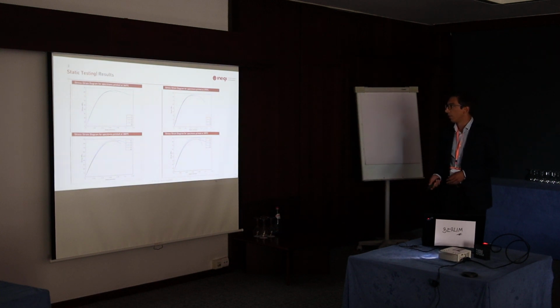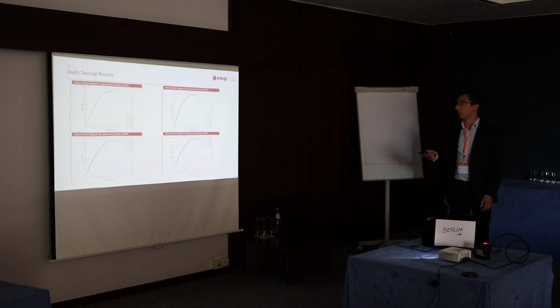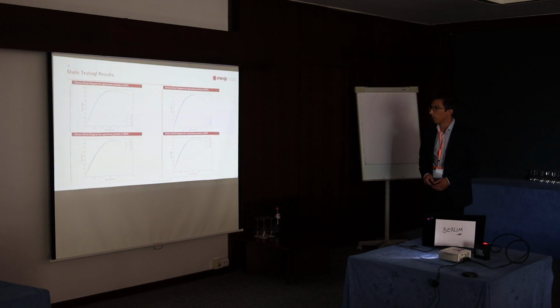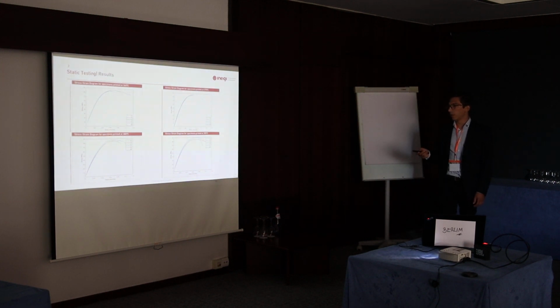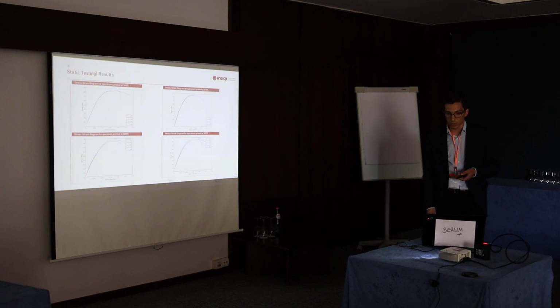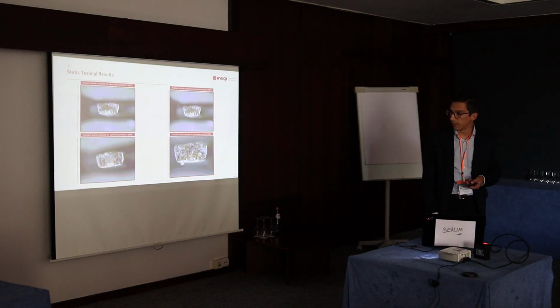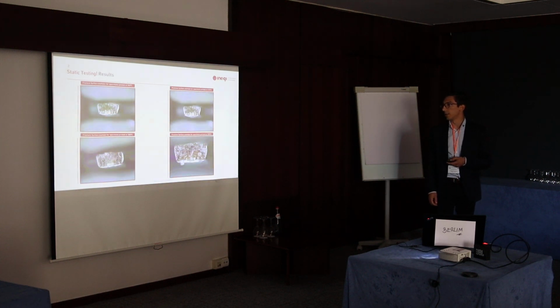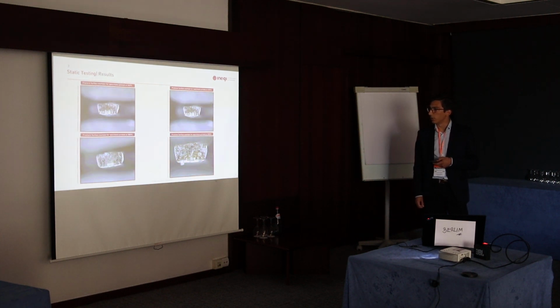The results shown are the following. So these are the strain stress curves for the 360, 370, 380 and 390 degrees of printing. We didn't find any major difference, and we also find that the properties vary a lot even within the same range, which leads us to conclude that probably there are other factors influencing these specimens more than the temperature. We tried to even assess the fracture surfaces in order to find some clues on why this was happening, and we also couldn't find any major reasons from these images.